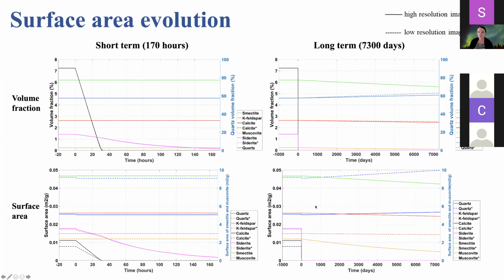At longer time scales, you can see an increase in quartz surface area due to precipitation, and then decreases, for example, with muscovite as muscovite starts to dissolve. That was not as evident necessarily in the volume fraction. The evolution of surface area mimics each other, where, for example, with quartz, they are parallel to each other, but really, the same kind of pattern is emerging here.